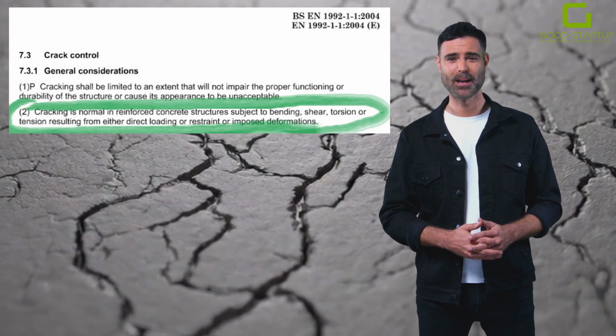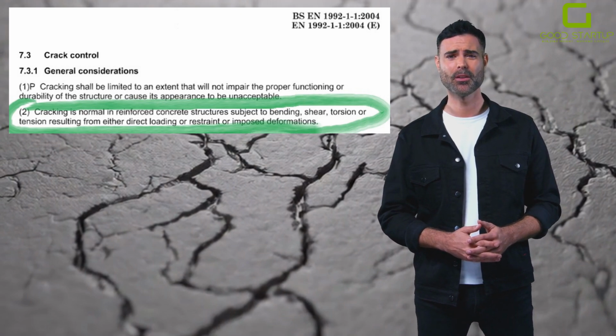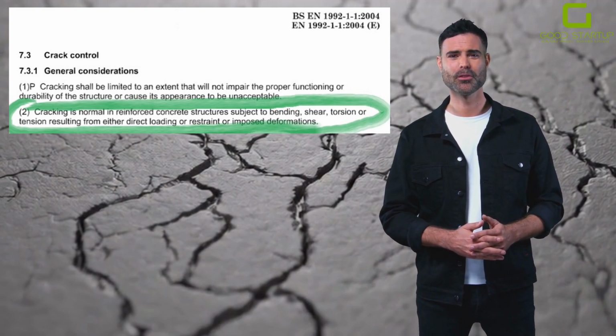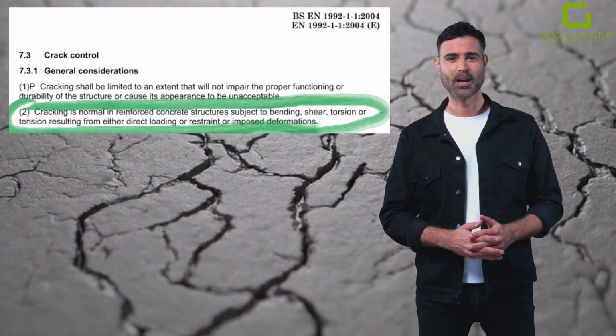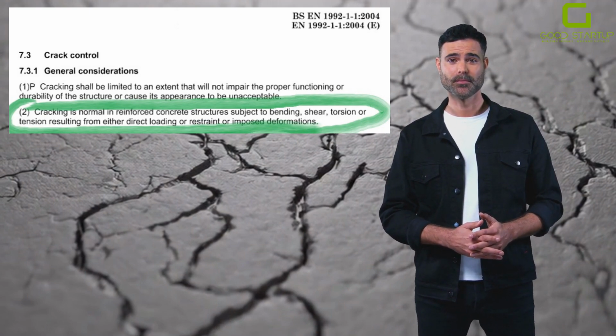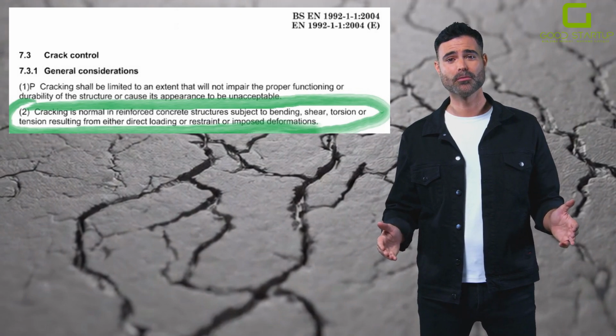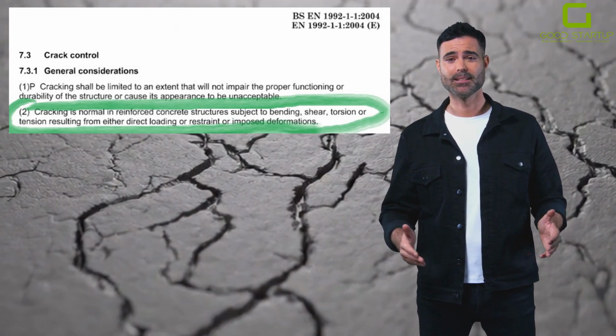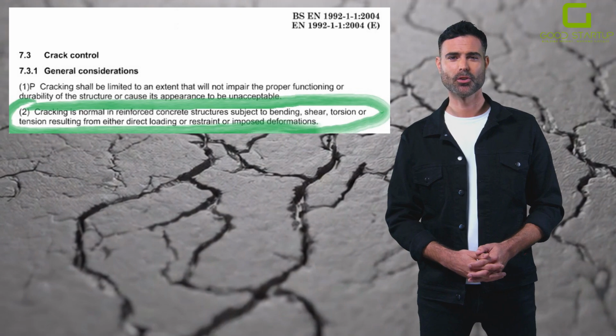Eurocode 2, EN 1992-1 assumes that if we limit crack widths to about 0.3 millimeters under normal use, the structure's durability and appearance will be acceptable. So the truth is, we design concrete to crack, but only in a controlled, fine pattern that is not deemed harmful. ACI, Eurocode, FIB, all agree that cracking is inevitable in reinforced concrete.